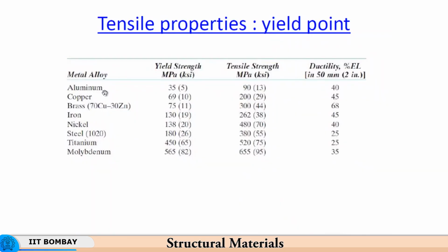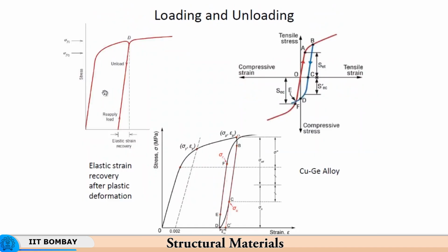Okay. So, you have the yield points of different materials which are given here, and then if you load and unload, this is what is shown over here. So, if you load and unload, now again you have to get the 0.2% proof stress. So, now this is the elastic recovery, and if you take a sample, load it up to a certain strain, unload it, and then you reload it, then it will again follow this curve, and you will find that it will yield here and it will continue further. So, if you were to join this, it will follow on the same curve, except for this cusp which is the result of loading and unloading.